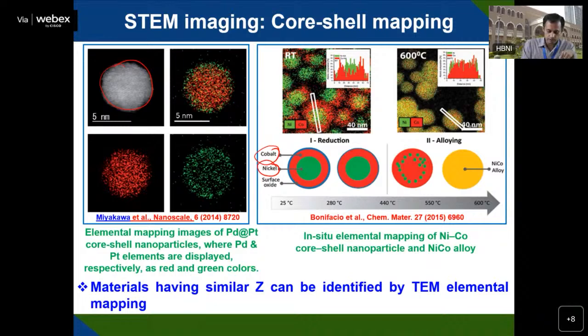So this green color and red color is mainly Pd and Pt. You can see the overlap image, how this Pd and Pt is distributed. The right image shows a cobalt nickel core-shell structure to alloy formation. You can see initially it is a core-shell structure, with nickel here and cobalt here. And then as you go on heating from 25 degrees to 600 degrees centigrade, slowly you are getting an alloy